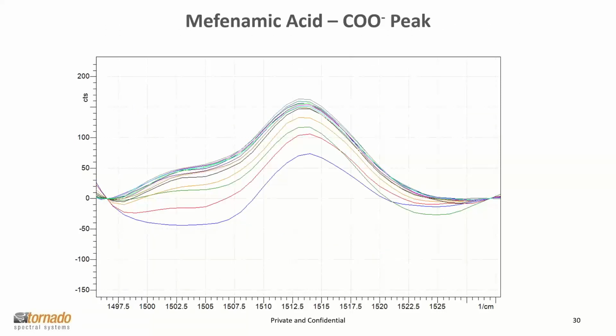But I'll also call your attention to another region of the spectrum, which I highlighted previously, and this is a region where the carboxylate peak appears. And oftentimes, or hopefully, when you see a peak disappear, you'll see other peaks start to appear. And this one was an interesting one. You can see that that carboxylate peak was present in a smaller intensity, which increased over time as the crystallization or crystal transformation occurred. But if you look very carefully over in this region, closer to 1500, you can see there is a peak that starts to form here that was not present initially in form 2, but does form as the crystal transformation takes place.